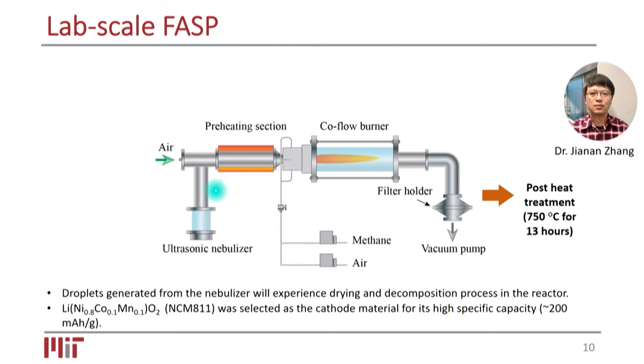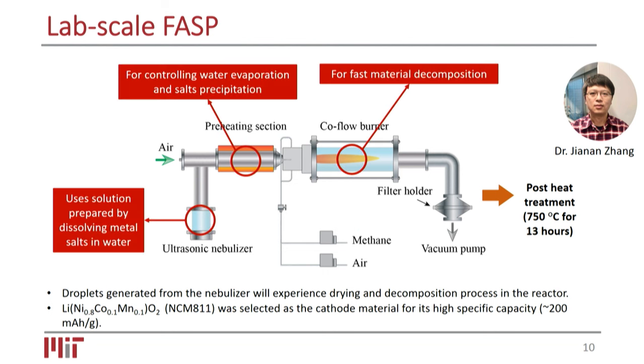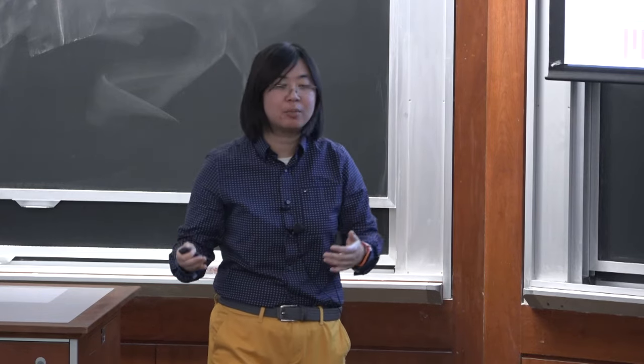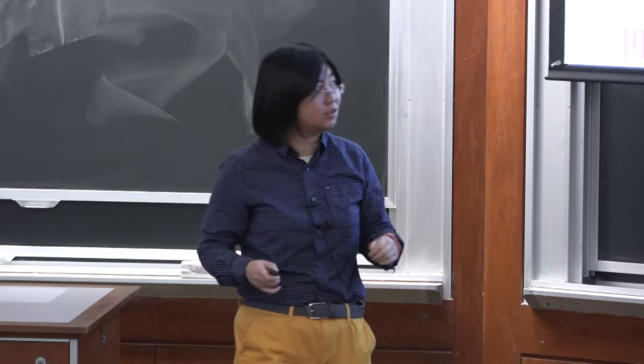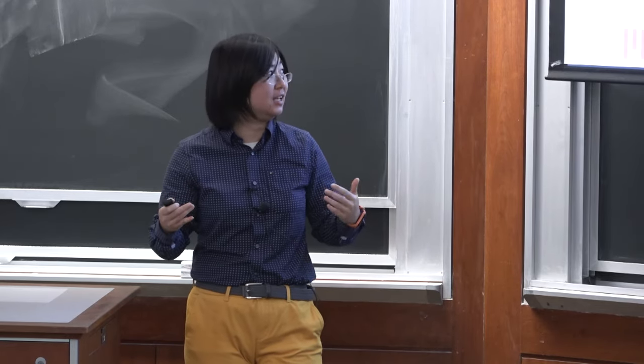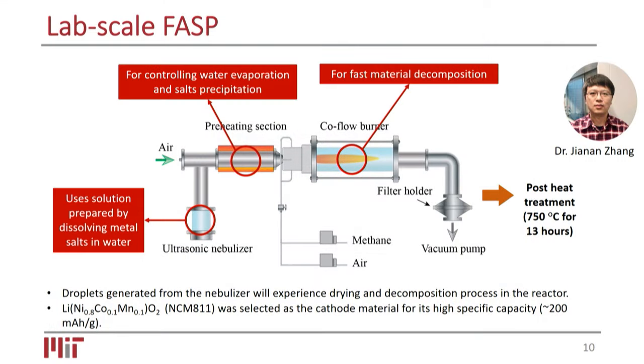We would have precursors coming into play in the form of solutions. We dissolve everything, so here is a difference compared to co-precipitation. Including lithium, we dissolve every precursor into water and spray that into the system in the form of fine droplets. During the process, that's where the reactor comes into play. Instead of having a single flame reactor, we tailor the entire thermal process by having a few sections, the preheating zone and the burner, to have fast heating. I will show you later how controlling these thermal processes is very important. Finally, after the flame zone, we can collect particles and characterize the material performance, et cetera.